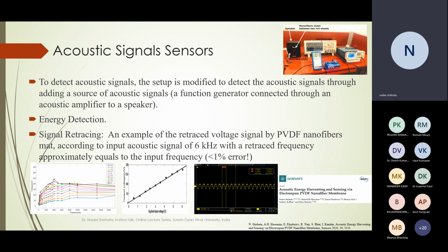So it can be used in energy harvesting or detection, but not only to this limit. It could be considered in some acoustic communication, especially if it could be developed underwater, for example. Our group had some work previously related to signal retracing. We were applying acoustic signals with different frequencies and amplitudes on PVDF nanofibers, and we found that some audible frequencies could be retraced with minimum distortion of the signal, with the output frequency very similar to the input frequency with minimum error. In the worst case, it was around 1% frequency error. This work was published in the Sensors journal in 2020, related to acoustic signal detection and retracing.